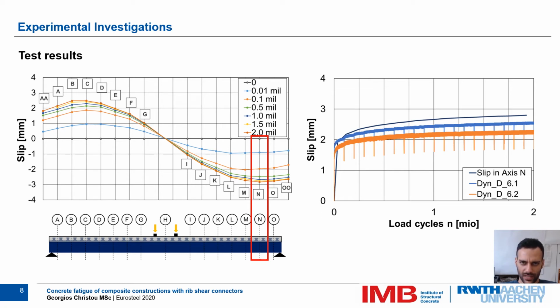Thus, the observed dowel near axis N is subjected to higher forces than the ones assumed. As the inelastic slip increases, the shear forces are redistributed, and the shear force near axis N decreases slightly as more load cycles are introduced. After the first fatigue phase is completed, in which significant slip increase is observed, the forces in each dowel can be assumed to remain constant and roughly equal over the length of the girder.